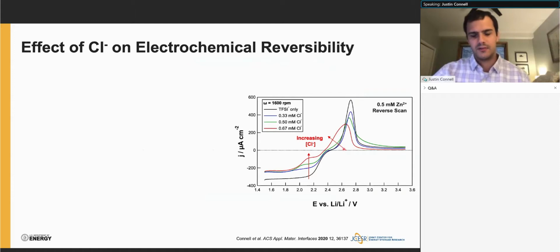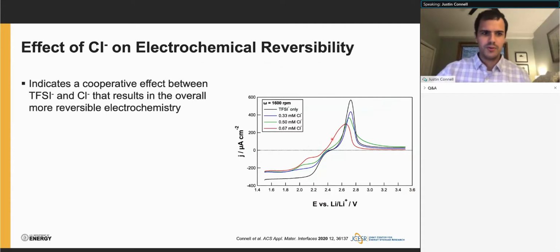Correspondingly, as we increase the chloride concentration, though, we see the onset of metal dissolution shift to lower overpotential, more negative potentials. And so what this suggests is a cooperative effect between TFSI and chloride that's resulting in the overall more reversible electrochemistry in the system.